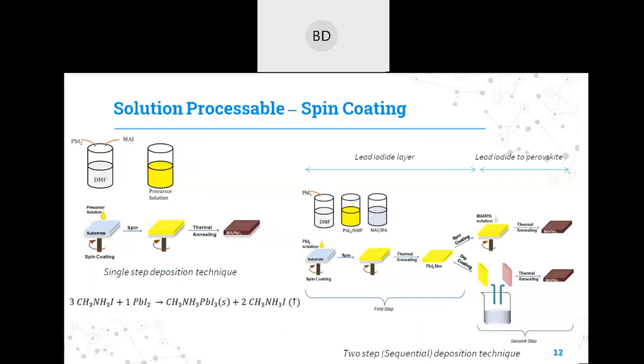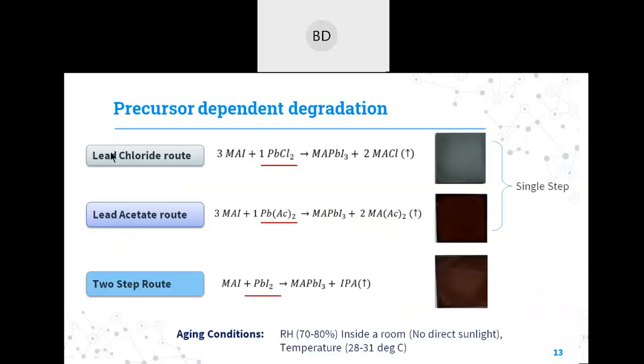We have also used these two methods only to understand the degradation mechanism in our studies. So what we have used, first, is the lead chloride route, where we have used methylammonium iodide and lead chloride as a salt, which gives the MAPbI3 structure. The second is the lead acetate route, where we have used lead acetate as the lead salt instead of lead chloride, and it gives the MAPbI3 structure.